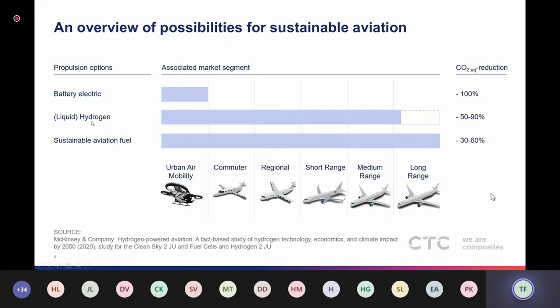So the second option is hydrogen, and I said here liquid hydrogen, because while hydrogen has a 2.8 times higher energy density per mass than kerosene, in the liquid form it just has 25% of the energy of kerosene per volume. So it takes 4 times the volume as a comparable kerosene tank. And in gaseous form with pressurized tanks, this is even bigger, so it takes even more volume. Therefore, it might be applicable for short range flight, but for everything longer, it's not really applicable. I will talk about the application on long range a little later on.